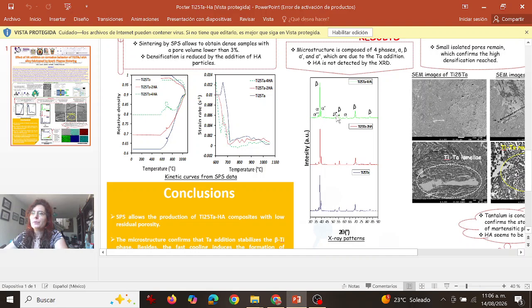So we have the alpha, we have the beta, and we also have the spikes corresponding to the alpha prime and also the alpha double prime. See? Alpha prime, alpha double prime. Another thing we can observe is that we have no spike for the hydroxyapatite, basically because it was too low. So we can say that hydroxyapatite is not detected by our X-ray diffractometer, at least not in this pattern. All right.